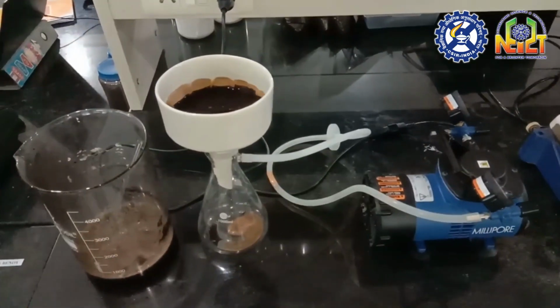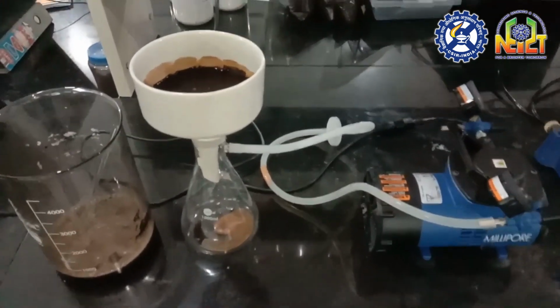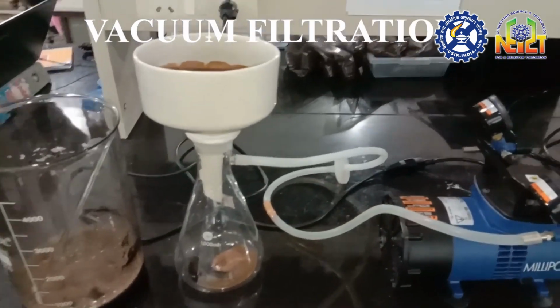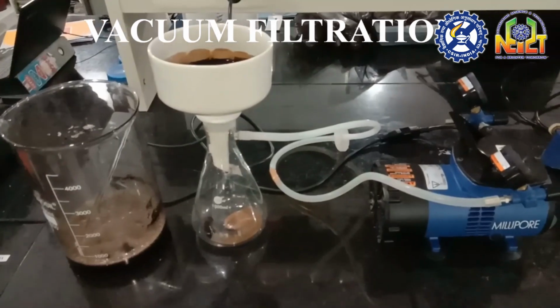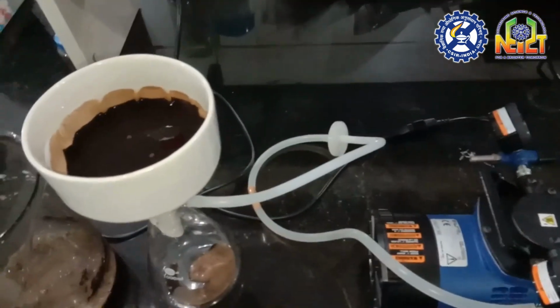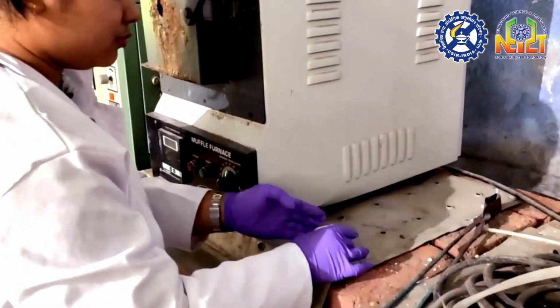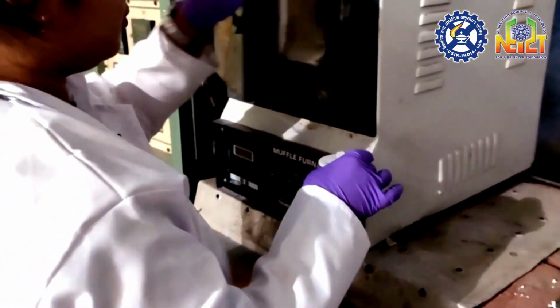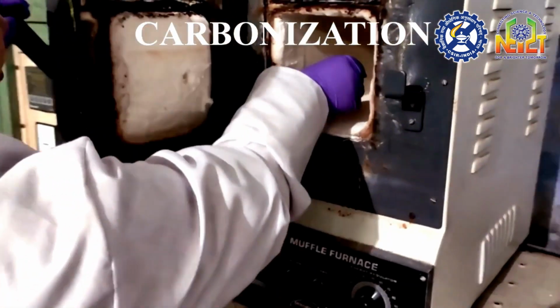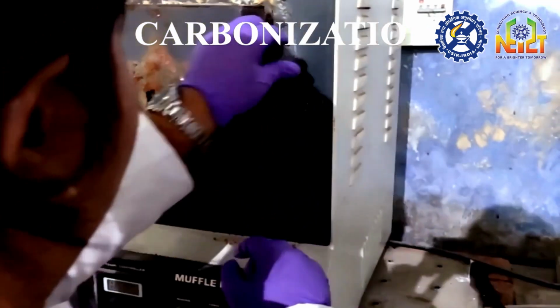After completion of the reaction, the mixture was cooled to room temperature and then filtered in a funnel using a vacuum pump. The dried oxidized coal was carbonized at 400 degrees Celsius in the furnace for about 2 hours.